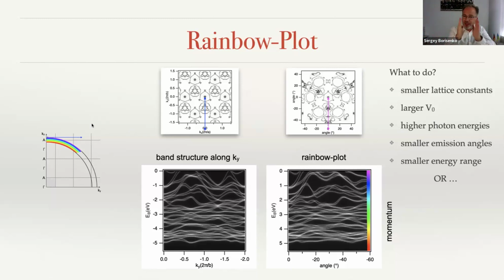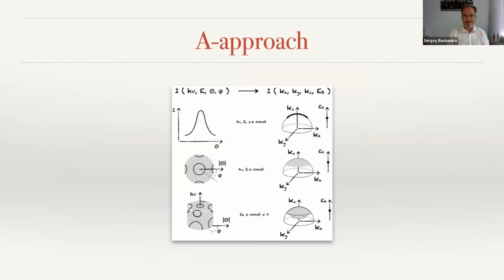One could go to smaller emission angles and measure just near the gamma point. Or one can consider a very small energy range. Of course, if we are staying close to the Fermi level, 100 millielectron volts or so, to determine superconducting gaps, renormalization, Fermi velocities, self-energy effects, this is fine. 100 meV is a very small fraction of the Brillouin zone. One can neglect it, and one could do this. But as soon as you see the plot which shows everything with the band structure, one has to be cautious.